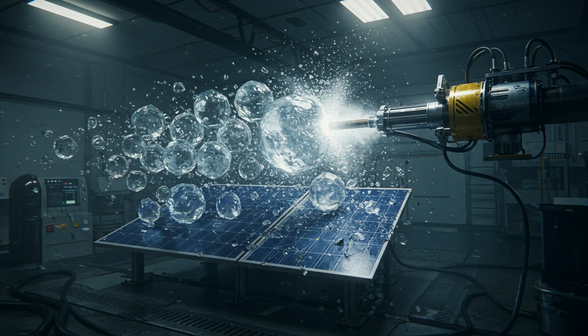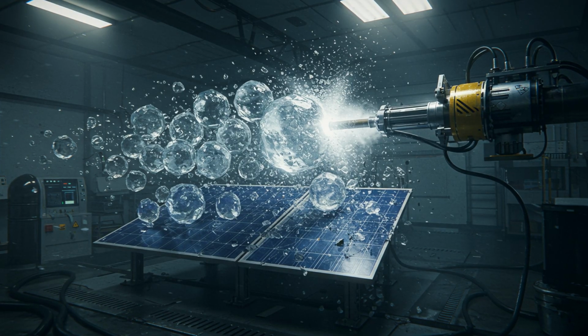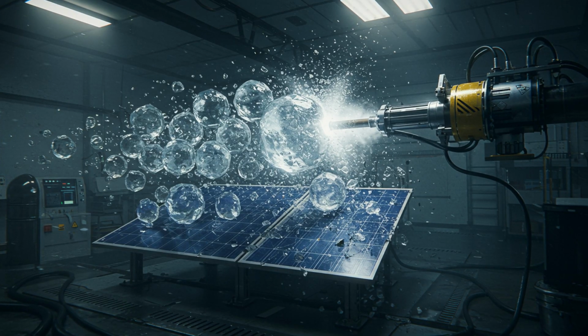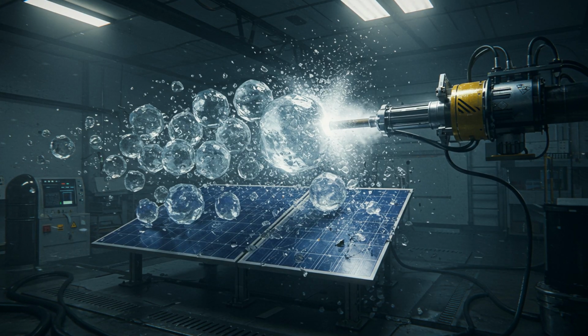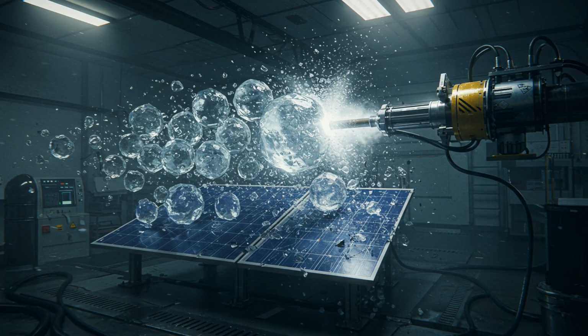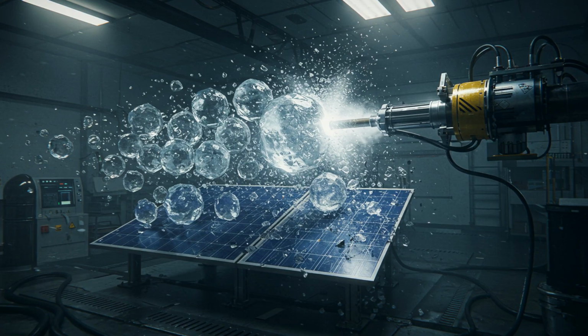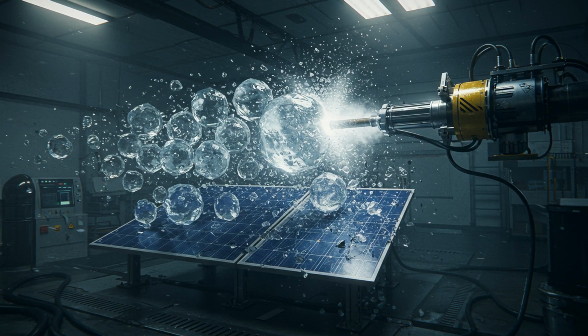Before a panel leaves the factory, it must prove it can survive 30 years of the worst weather on Earth. This is the torture test. Panels are placed in climatic chambers where they are cycled from 40 degrees below zero to 185 degrees Fahrenheit, hundreds of times, to simulate decades of thermal expansion. Next comes the hail test. Pneumatic cannons fire 1-inch ice balls at the panel at speeds of over 50 miles per hour. The tempered glass must hold firm without cracking.